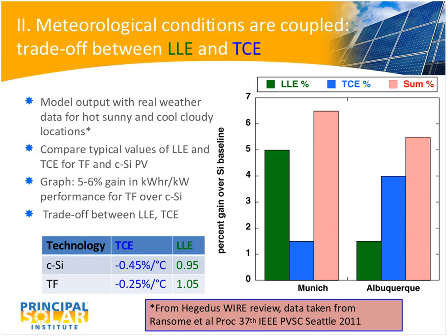In contrast, in Albuquerque, where they have a lot of direct sunlight all year, the effect of the low light efficiency isn't so big, but the temperature coefficient is where you get the primary gain. So when you add the two together, it turns out that in either location, the thin film module would outproduce the crystalline silicon by, let's say, 5 to 6%.